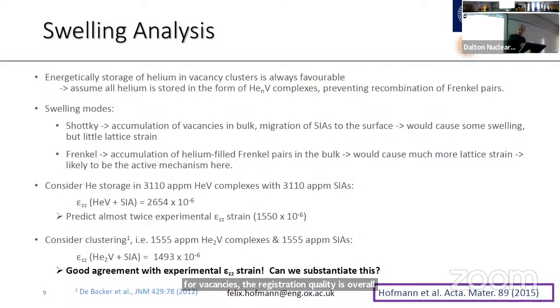So we can then go through and say, well, okay, can we analyze this swelling? Energetically, it should always be favorable for helium to live inside vacancies, rather than interstitially in the lattice. So let's assume that everything lives in helium-vacancy complexes. And you could then imagine two types of defect accumulation. One, where you just have the vacancies that are retained in the material, and all the interstitials, because interstitials in tungsten are very mobile, all escape to some surface, right? Based on what I've just told you, that would suggest that we should have a negative lattice strain, so a contraction of the lattice, because we have an excess of vacancies. That's not what we see.